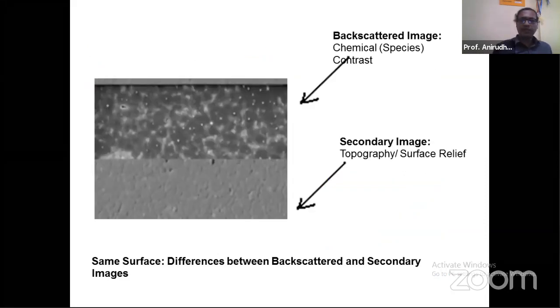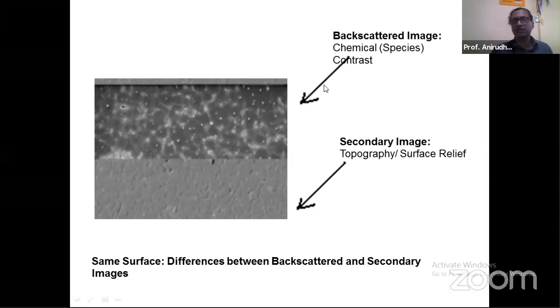So this picture shows a backscattered image. It is the same base plate. I mean, the base information is the same, but it is the image when we use two different informations. The top one is when we are using the backscattered electrons, and the bottom one shows the same spot when we are using the secondary image. So when we are using the backscattered image, it shows areas corresponding to different distribution of species. For example, you can see the zone where it is fairly homogeneous and belonging to one species, whereas you see different spots perhaps belonging to another species. While coming to the bottom half of this image, which is from a secondary image, that information is lost. Instead, it is showing the surface relief or the undulations and peaks on that very same surface.